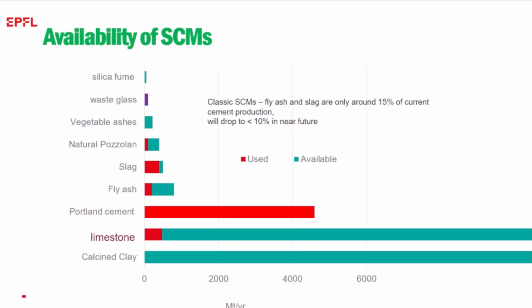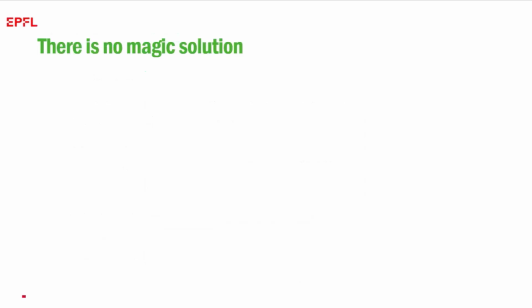Slag, very limited supplies, already all used. Fly ash already quite limited and going to go down, but a very variable product, so it's quite difficult to use all of it. Limestone we have a lot of, but when we go above levels of about 15%, we simply have a dilution, which doesn't really help anything. And then we've got clays that can be calcined.